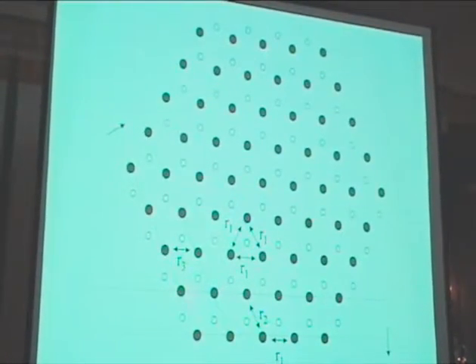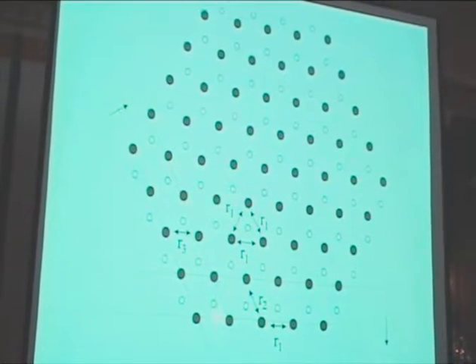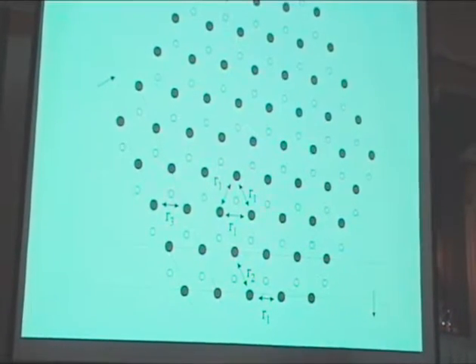So we took 2 rows at the outside to be different. And we allowed it to be different in many ways. We had in general 3 models. In all models, all atoms could be randomly positioned. However, the molybdenum to sulfur distance was always kept the same, 2.41, because the EXAFS showed that that distance never changed, and also that coordination number never changed, and also from an inorganic chemistry point of view, this is the nearest neighbor. So that's the strongest bond. So that's a stiff bond. So there's all reason to believe there is nothing wrong with that, and you don't have to randomize that.